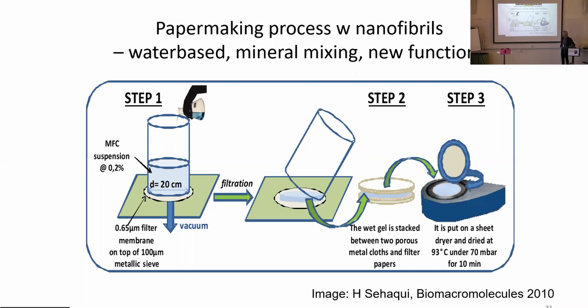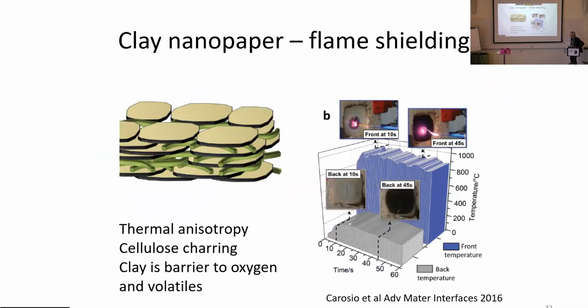And one advantage is, of course, that since you have a colloidal suspension, you can mix in other particles. And then when you dry the film, you have these particles distributed, and you don't need any binder. You use the intrinsic properties of the cellulose fibrils, and you bind a material that is solid and coherent. So one example is clay nanopaper. So this is from a project run by Lars, funded by SSF. So we mixed clay platelets, a very low-cost material, but these silicate platelets have excellent mechanical properties. So we're mixing this together.